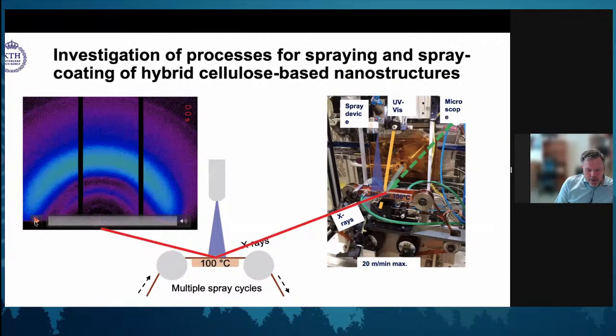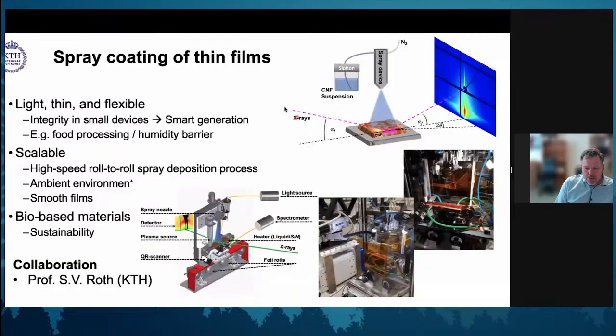Looking at what you get if you use X-rays, so going back one step with grazing incidence coming in, in this case it's X-rays. We will see the effect of spraying on a surface. The reflection you get from the X-rays will be dependent on the nanostructure of this film. So this pattern that we will see is directly dependent on what happens on the surface.